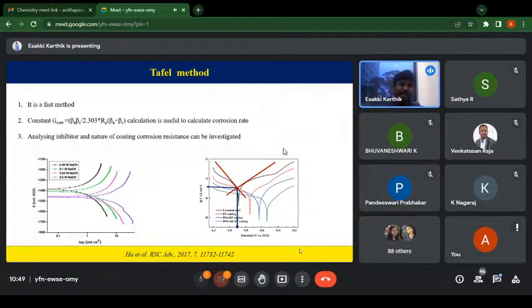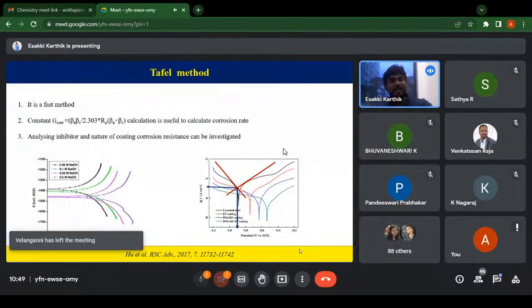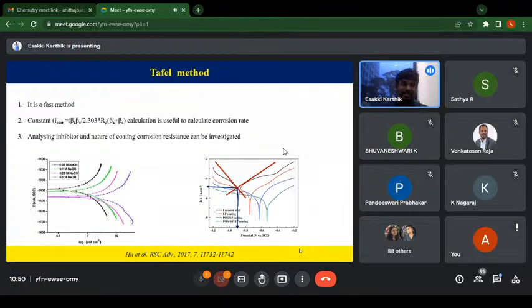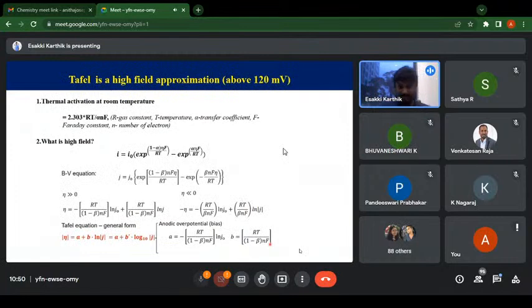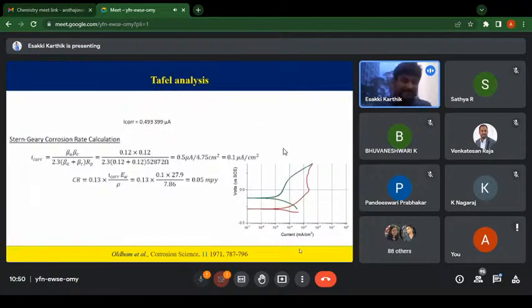When you take the slope of these two lines and put them in that equation, we already know the corrosion resistance. Using equation number 2, you can calculate Icorr. This is the Stern-Geary corrosion rate calculation. Here they have measured 0.1 microampere per centimeter square. Then, based on that Icorr, once you know the material's equivalent weight and density, you can easily calculate the mils per year.